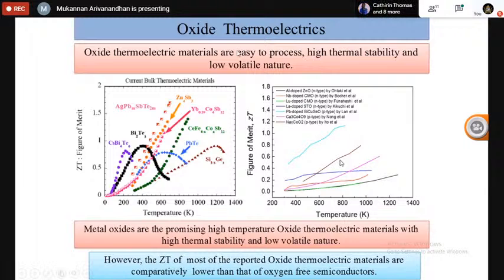But the main important difference is the figure of merit. The figure of merit is quite high for the semiconductor-based materials, even up to 2, and nowadays more than 2.5 they have realized. For the oxide-based thermoelectric materials, the figure of merit is mostly less than 1, right? So this is the scenario. Although they are thermally stable, the performance is not up to the level.